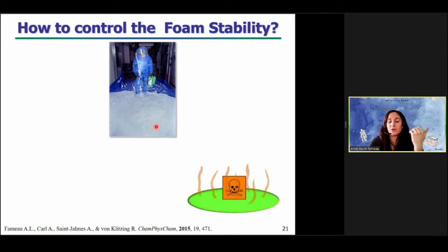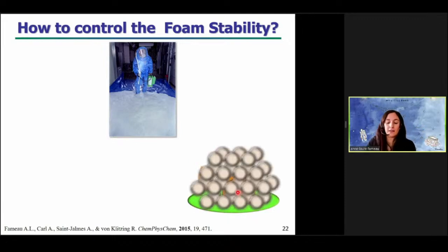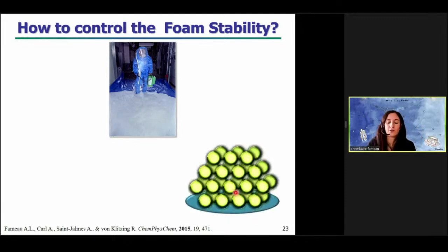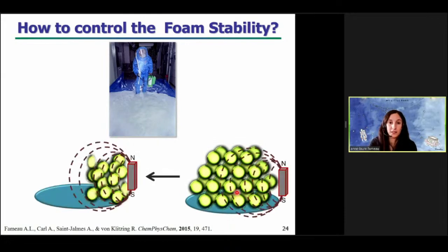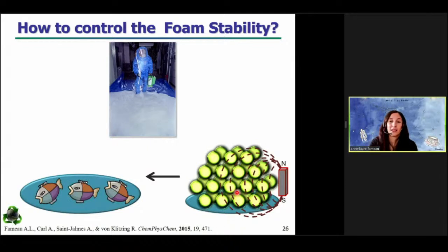For example, if you have a surface to decontaminate, you put a foam on the surface, the foam acts on this surface, but then if you can use an external stimulus, for example, such as drawn here, a magnetic field, to destroy the foam on demand, then the guy just needs to remove the small quantity of contaminated liquid remaining. And you don't need to use chemical defoaming agents, which can be very harmful to the environment, to destroy the foam at the end of your process.